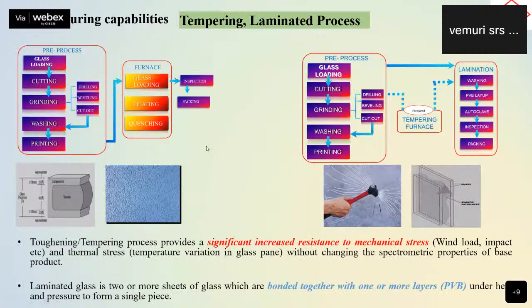And after doing such glass coating of these materials, the main problem of electrochromic coating is that it cannot withstand higher tempering capability or higher tempering lamination process during quenching and heating the glass after doing the coating, because the coated glass substrate without anneal we cannot sell to the companies or customers. So we need to withstand such glass at a higher temperature, with 650 degrees quenching or furnace tempering.